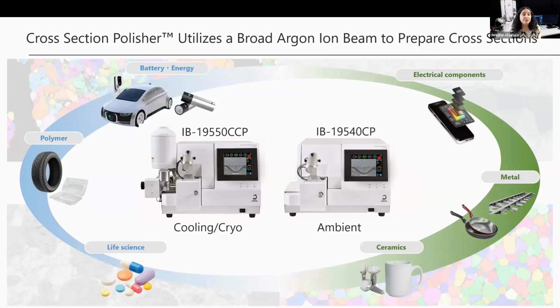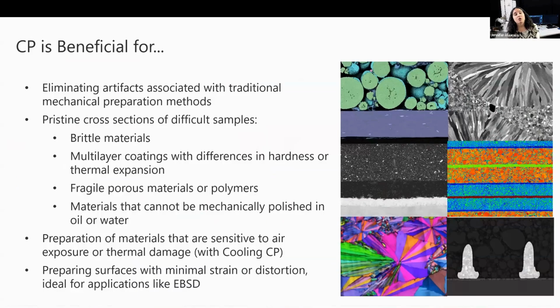JEOL's cross-section polisher plays a vital role in producing high-quality lithium-ion battery cross-sections for high-resolution imaging and analysis. One of the key advantages of using JEOL's cross-section polisher, or CP, is its ability to eliminate artifacts commonly introduced by traditional mechanical preparation methods. The CP enables the creation of pristine cross-sections in challenging sample types and produces surfaces with minimal mechanical strain and distortion, making it particularly well suited for surface-sensitive analytical applications.